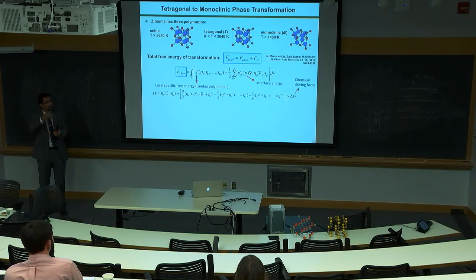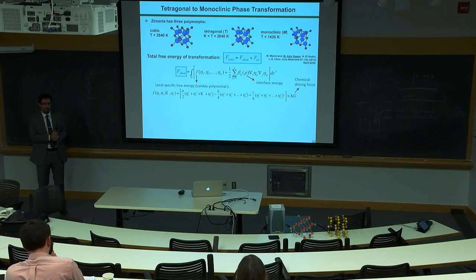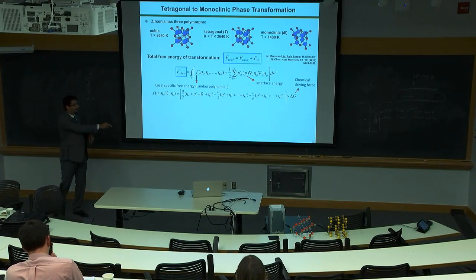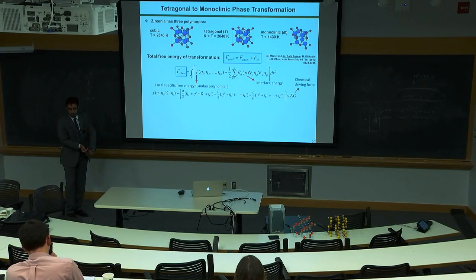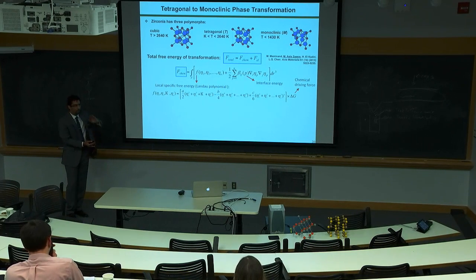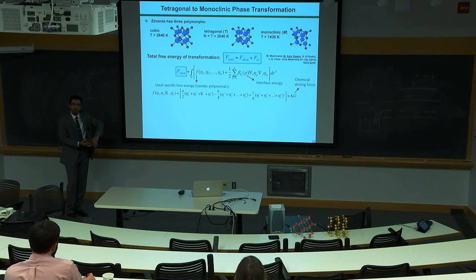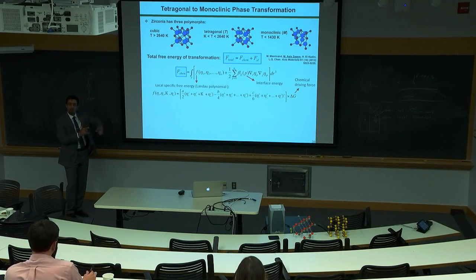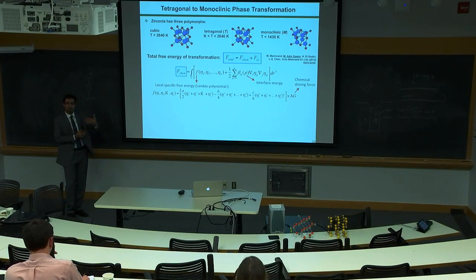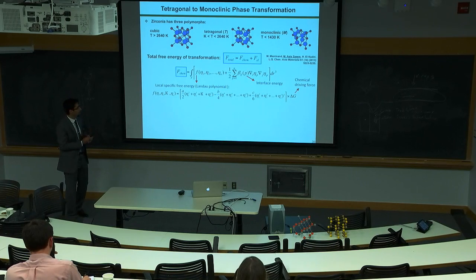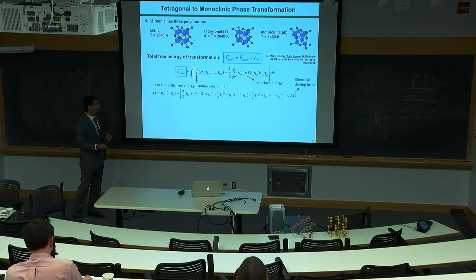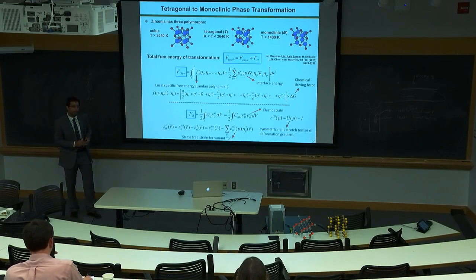Matrix and the transformed phase, okay? So if you have that, you can have it from thermodynamic calculations from phase diagrams. You can calculate it from density functional theory. It could be related to cohesive energy, also from molecular dynamics, atomistic simulations. The last part, elastic strain energy, is also a routine procedure for this,